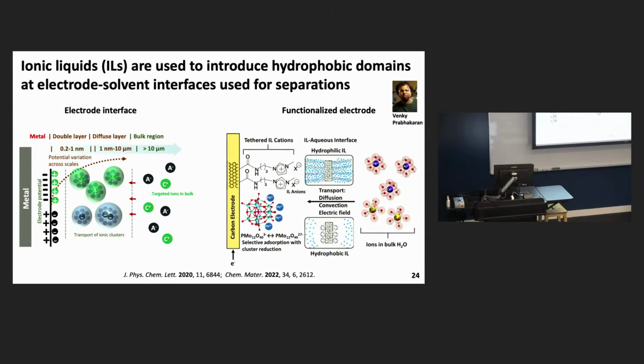It turns out that the transport and also the interactions with that double layer depend quite dramatically on the local environment at the electrode. So we've been playing around with ways to tune that local environment to try to reduce the energy barriers to desolvation and adsorption. And one way we've been doing that is by introducing ionic liquids to create hydrophobic domains at electrodes that help to strip that solvation shell from surrounding metal cations.